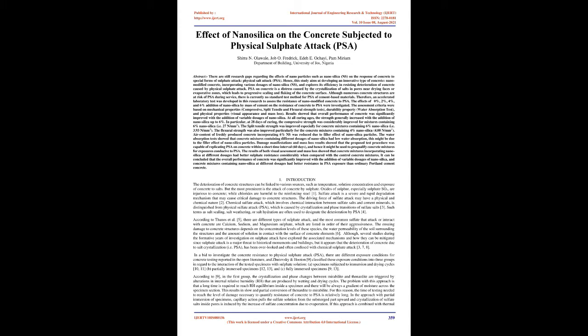Damage manifestations and mass loss results showed that the proposed test procedure was capable of replicating PSA on concrete within a short time interval, 60 days, and hence it might be used to pre-qualify concrete mixtures for exposures conducive to PSA. The results of both visual assessment and mass loss showed that concrete mixtures incorporating nano-silica at different dosages had better sulfate resistance considerably when compared with the control concrete mixtures.